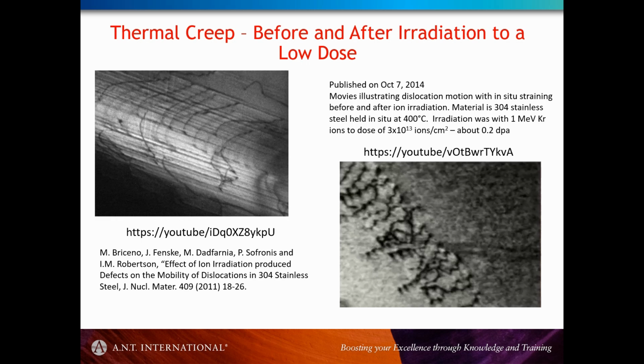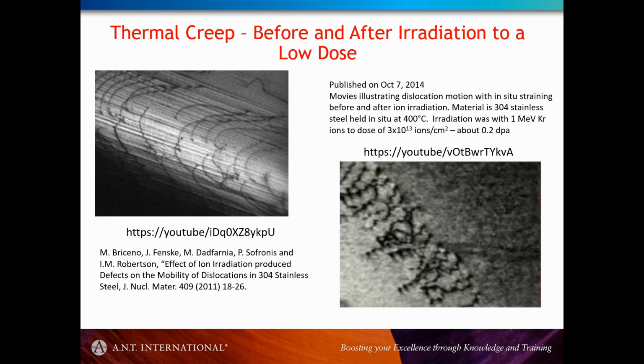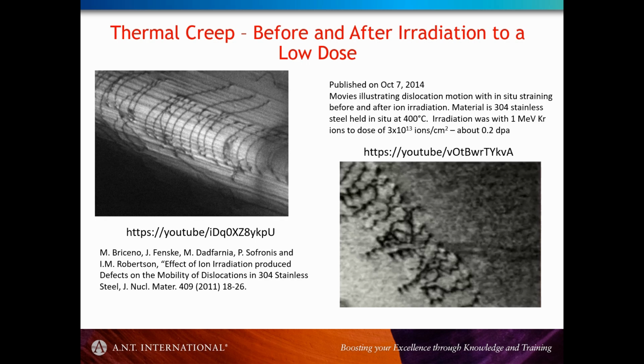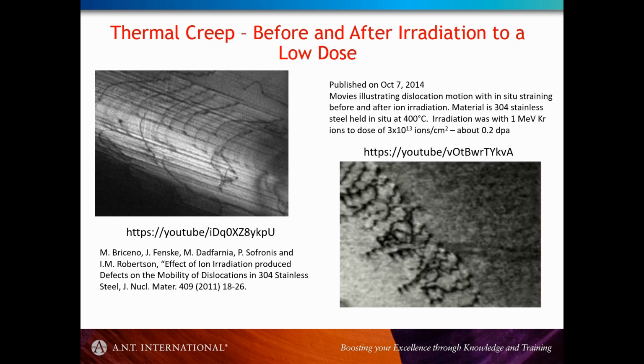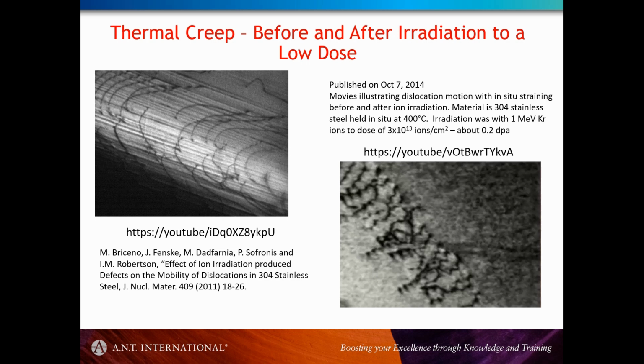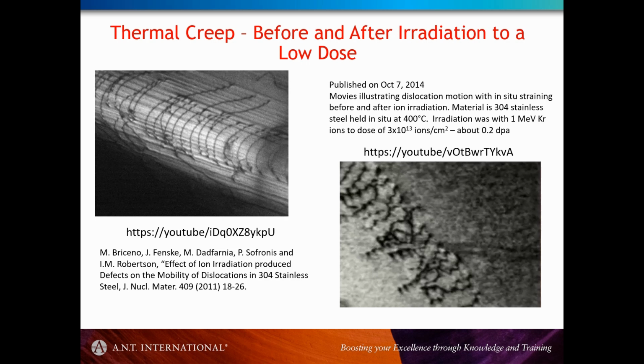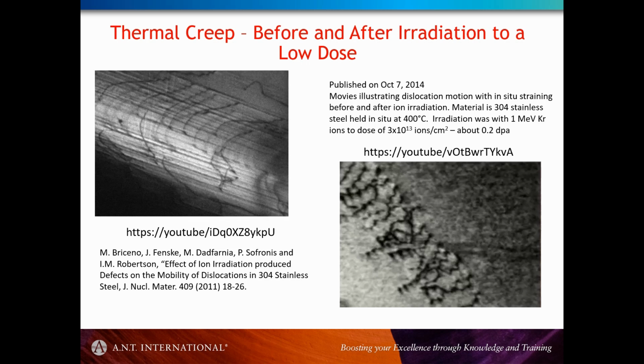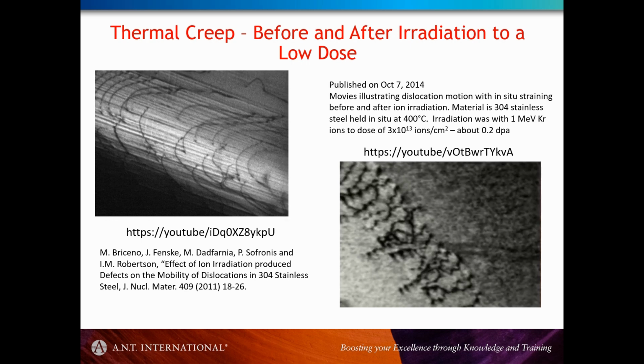This is off the internet, and this is some work by Briceno and I.M. Robertson's group, showing the effect of how dislocations glide in an unirradiated case. But then if you irradiate it, basically it's more difficult for the dislocations to glide.